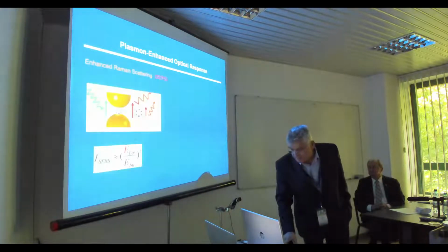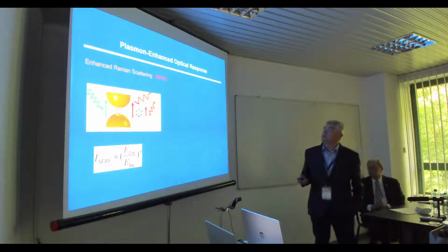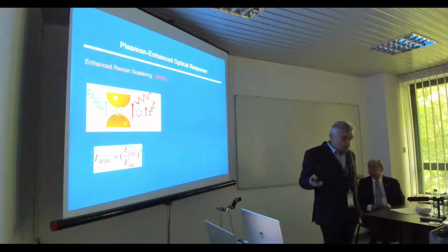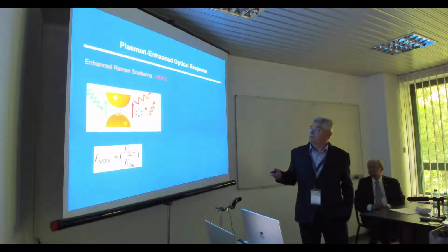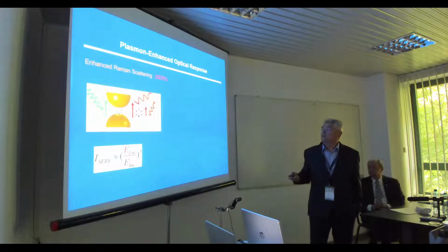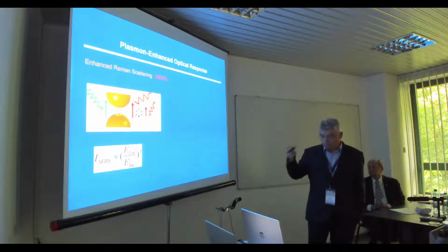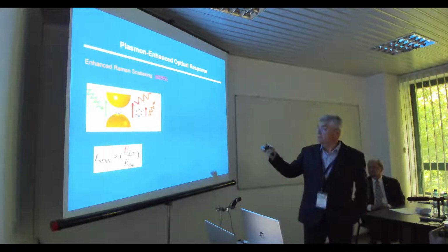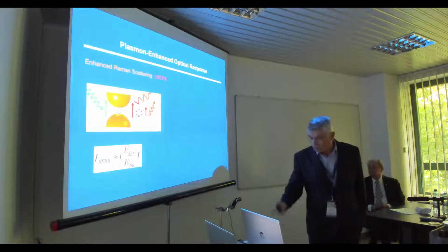My colleague already presented this effect, which is very useful. It is called surface enhanced Raman spectroscopy, and between the nanoparticles there is a specific hotspot where the field is even higher. By this relation you can understand that the intensity is enhanced, and the spectral signature is also enhanced. You can even detect a single molecule in this kind of hotspot.